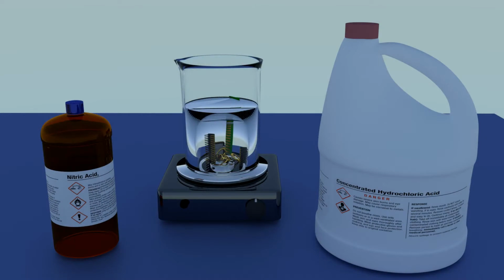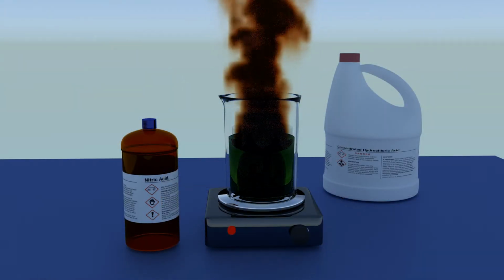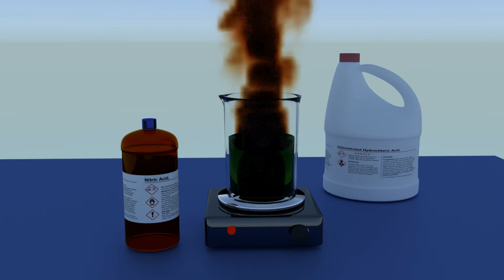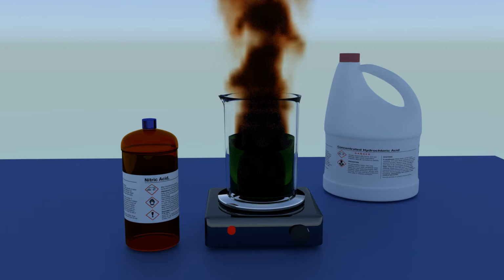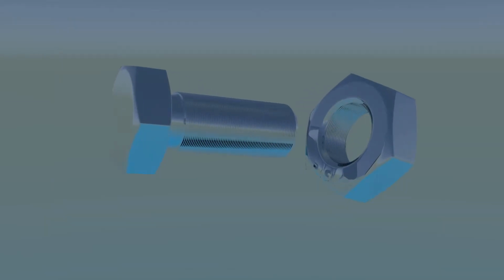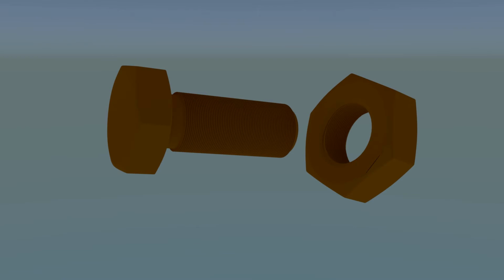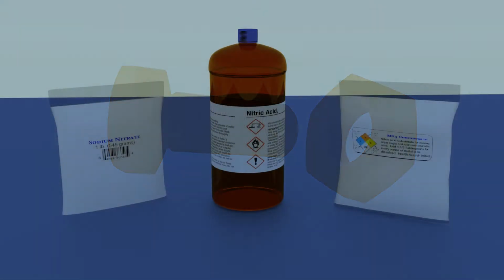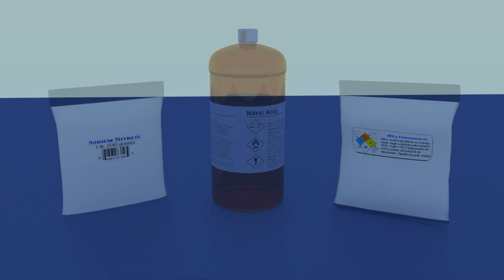The traditional form of aqua regia is a combination of nitric and hydrochloric acid. Nitric acid is very hazardous. When combined with hydrochloric and metal, it produces prodigious amounts of brown, very corrosive, toxic gases, including nitrogen dioxide. These fumes are so corrosive that they will rust even high-grade stainless steel, after less than 1 second of exposure. In these instructions, we will include the nitric acid version of aqua regia, but really, there is no good reason to use nitric acid. It is dangerous, expensive, and difficult to obtain. The dry substitutes, either MX3 or sodium nitrate, are far safer, reasonably priced, and easily obtained.